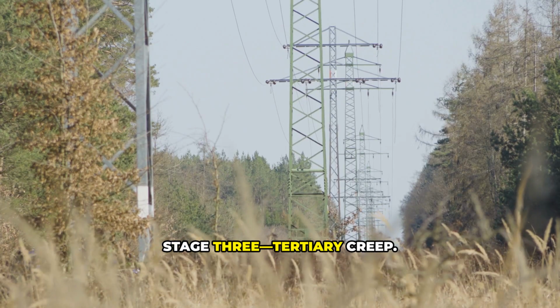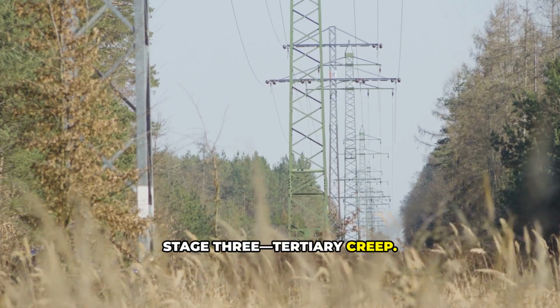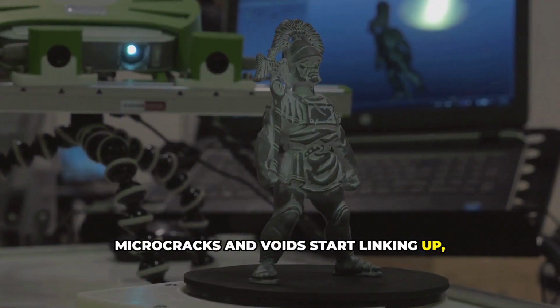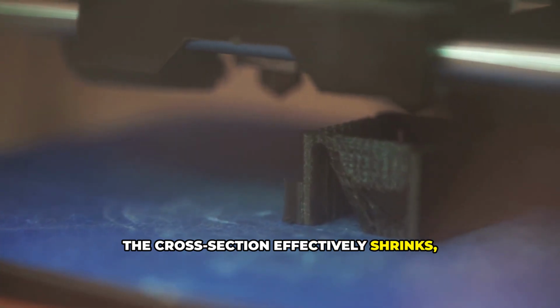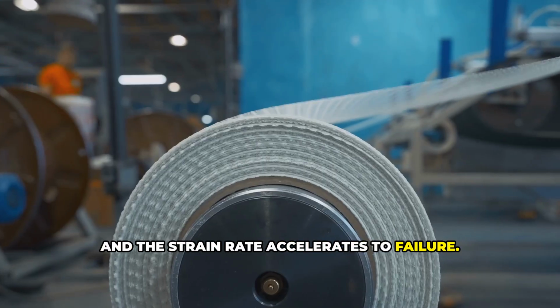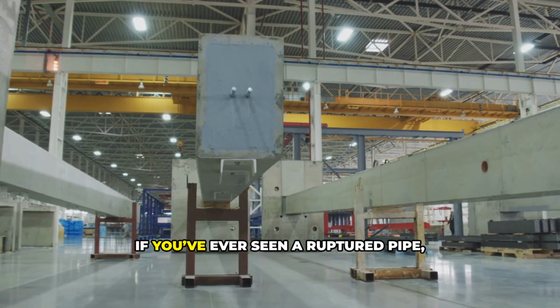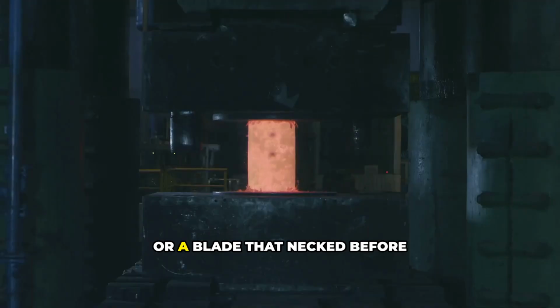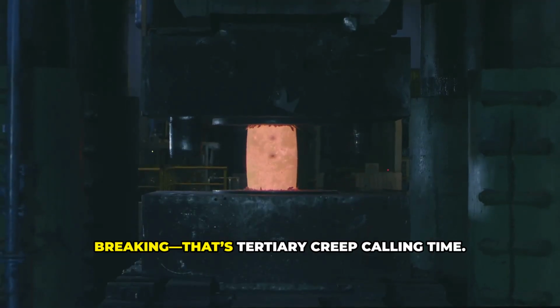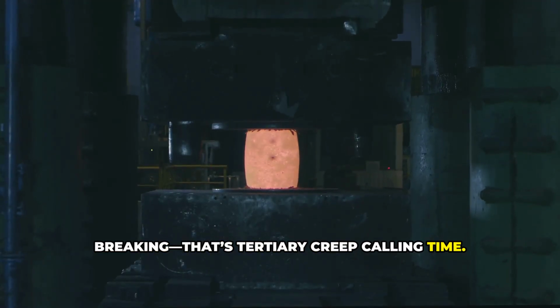Stage 3, tertiary creep. Microcracks and voids start linking up. The cross-section effectively shrinks, and the strain rate accelerates to failure. If you've ever seen a ruptured pipe, or a blade that necked before breaking, that's tertiary creep calling time.